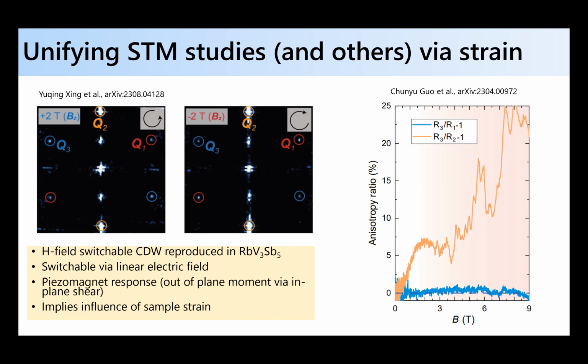But then they encapsulated the crystal in glue to remove strain and made a device, and they carefully removed the strain as much as they could. And that term went away. Basically the anisotropy goes away when they look at the in-plane transport. But then if they look at that strain-free crystal and apply an out-of-plane magnetic field, they can see that it comes back. So this, to me, implies that there is a piezomagnetic term, and the most straightforward explanation is some subtle time reversal symmetry breaking in the CDW state. This is a conjecture at the moment, but I think it might unify these two observations and also explain why there's such variance in the literature, because of this uncontrolled strain effect. So hopefully this gives us some guideposts moving forward on how to look at these materials.